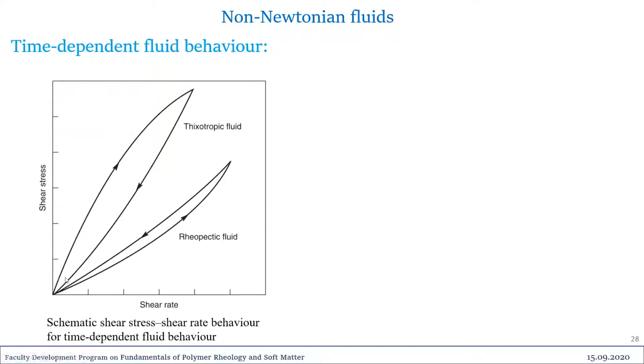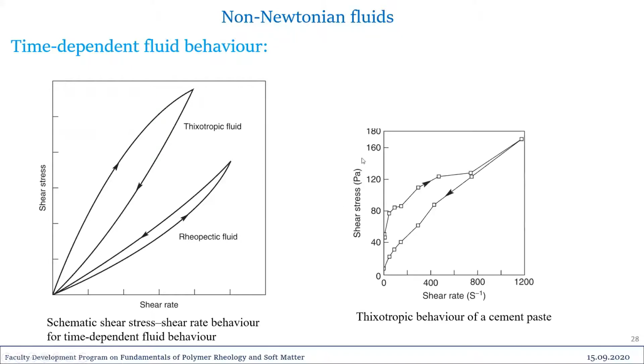In rheopectic fluid, as the shear rate increases, the viscosity also increases, but it has a completely reversed hysteresis loop compared to the thixotropic one. So why are we observing such behavior? This is the example of cement paste, which has a thixotropic behavior, and these are the real data with the shear rate. You are able to see that this path is not followed by the reverse experiment.